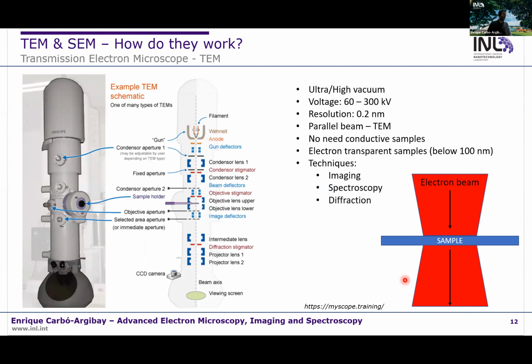So on the other side of the SEM, we have the TEM, transmission electron microscopy. The main difference between an SEM and a TEM is the mode in which we analyze the sample. In an SEM, we have an electronic probe scanning the sample. The sample can be a bulk sample. We don't need thin samples. However, in a TEM, the sample is not at the bottom of the column. It's in the middle of the column because we need the accelerated electrons to go through the sample. So for that reason, we need very thin samples. Very thin samples refers to something below 100 nanometers.